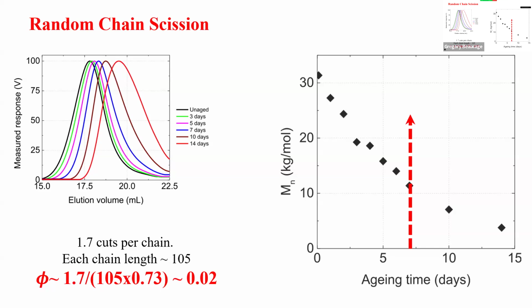So I made 3 pieces, which means I had to put 2 cuts in it, right? So this is all I'm saying. Roughly, when you do the exact math, it's 1.7 cuts per chain, all right? So I have 1.7 cuts per chain. The chain length was 105. It's 27% crystal, so the cuts are only happening in the amorphous phase.